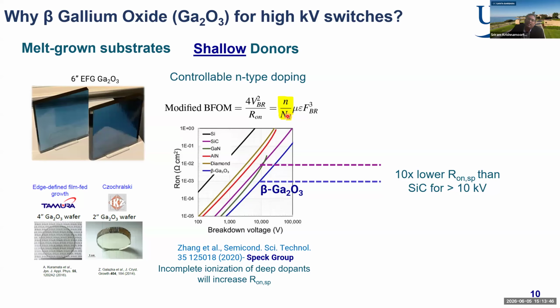And that's important because in other materials like diamond, which would be the ultimate material in terms of band gap, or aluminum nitride, it's harder to get shallow dopants, right? And why is that important? Because you need shallow dopants, you need full ionization at room temperature for the on state to get enough carriers to reduce the resistance of the switch. But if you don't have a shallow dopant, then you end up putting a lot more dopants to get fewer electrons. That's okay. But under reverse bias, these dopants can field ionize and create a much higher electric field.